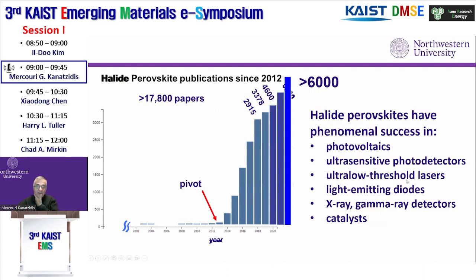So the halide perovskites were known already for a long time before that, but no one cared until these three publications that came out in 2012. You see here publications on halide perovskites before 2012 and after 2012, and it skyrocketed since then. People demonstrated tremendous performance progress, as well as other devices: ultra-sensitive photodetectors, ultra-low threshold lasers, light-emitting diodes, gamma and X-ray detectors, and now even catalysts and other things. It's incredible what's going on. We never expected that this would happen back in 2012.